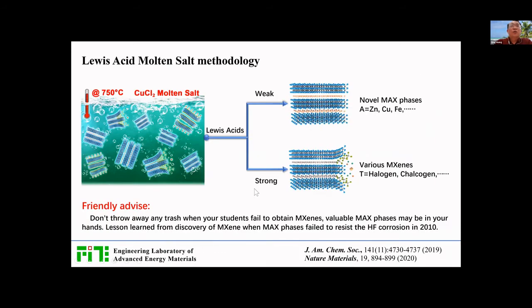So I want to make a simple conclusion of our synthesis methodologies. If we use molten salt and use its Lewis acid properties, if the Lewis acid is very weak, we could get some novel MAX phases. That means we can change the A element into zinc, copper, iron. So it naturally can broaden the properties of these materials. And if we use a stronger melt, we can easily etch out the A element and get some interesting MXenes. And more important is that we can control the terminations of these newly formed MXenes.